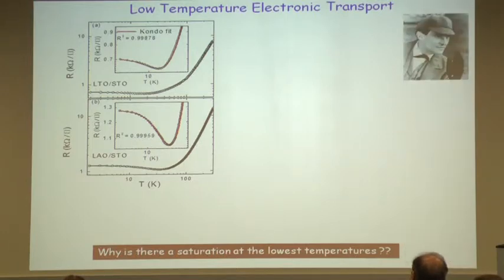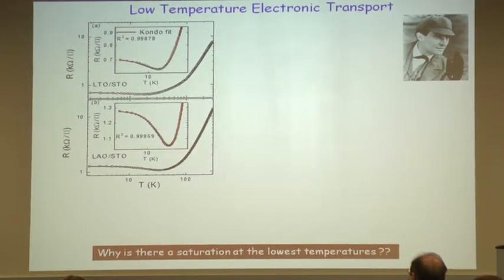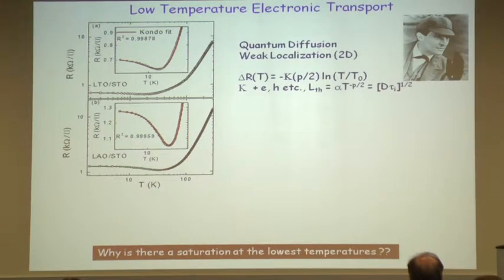To figure this out, you really have to be a Sherlock Holmes, because there are several competing interactions which contribute to this. And the very first is the so-called weak localization, or the quantum diffusion in 2D. And if you look at the behavior there, the change in resistance goes as log of T. And that's what we see over here.